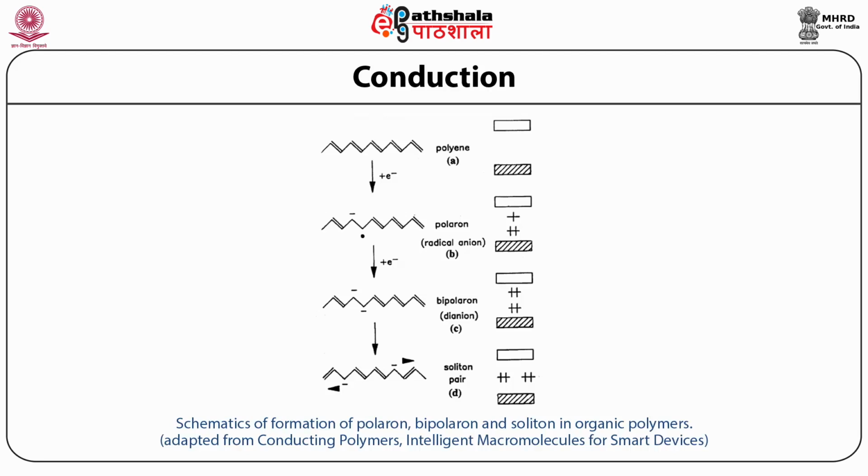In polymeric materials such as trans-polyacetylene, which have a degenerate ground state, the bipolarons can further lower their energy by dissociating into two spinless solitons forming at the mid-gap location.